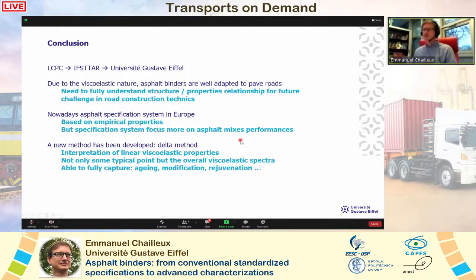In this method, we not only take some typical point on the curve at certain temperature, certain frequency, but we are observing the overall viscoelastic spectra in order to be close to the internal molecular structure of asphalt. And you have seen that we are able with this method to fully capture aging, modification, rejuvenation, and we hope we can go further with this method, and perhaps up to perhaps a specification.